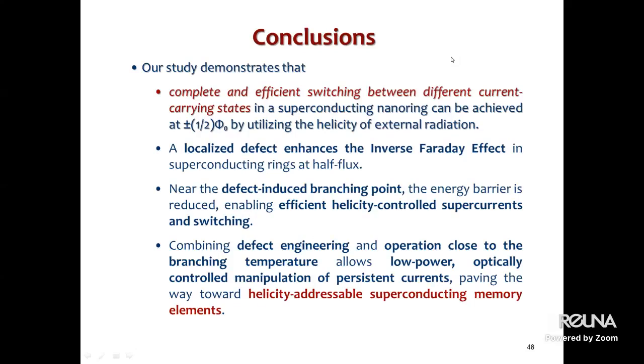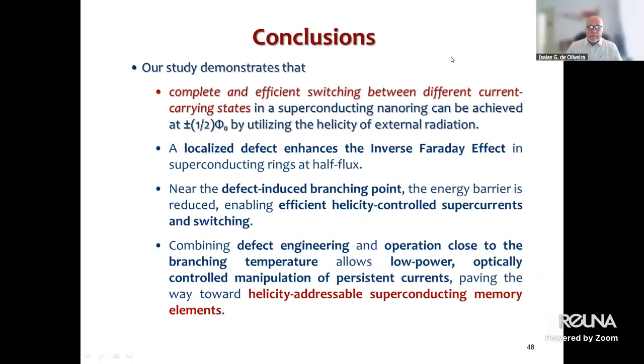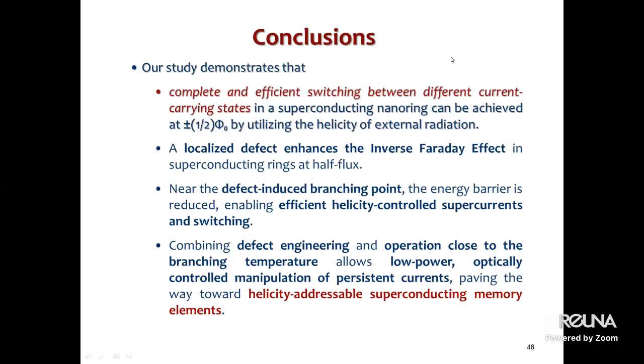You mean how to achieve half magnetic flux quantum? Yeah. Taking the geometry of the sample, I understand that you mean that we have a rather small ring of the order of, let's say, 5 to 10 ξ, that means coherence length. It's quite small, but diamond-based magnetic field detectors or SQUIDs allow tuning the magnetic field very precisely. So I don't think it's a problem to tune to half quantum exactly. On top of that, I investigated the stability of the results with respect to deviation from half quantum, and I showed that, for example, 0.45 flux also gives rise to the switching effect.